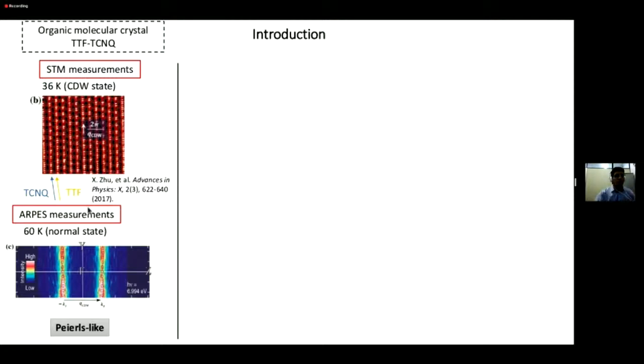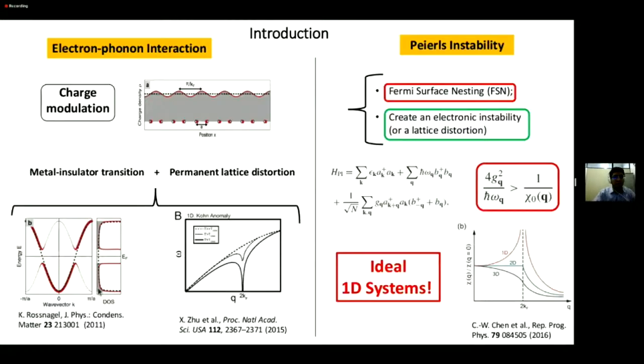We have two weakly coupled chains. And when people start decreasing the temperature, you create these modulations where you see here in this figure, where the more clear spots, we have more electrons, and the not so clear spots, we have fewer electrons. So basically it happens for the same wave vector that we see, for instance, here in the ARPES measurements for 2kF. That's exactly the Peierls instability result that we see.